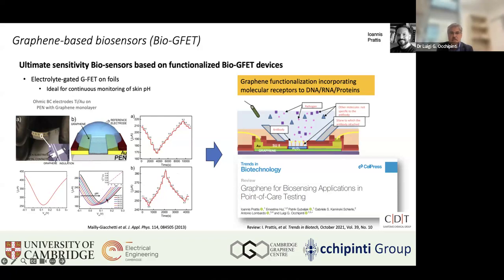Basically, graphene field effect transistors are, as you know, ambipolar by nature. The point where the conduction moves from holes to electrons is called the Dirac point, and the Dirac point is influenced by the doping of the channel or other molecules present that interact with the channel during the conduction. In fact, we demonstrated that as a pH sensor, because hydrogen ion molecules in a solution are easily shifting the Dirac point, which is actually used as the sensing mechanism, and also with a very good reproducibility and linearity as compared to the pH range.